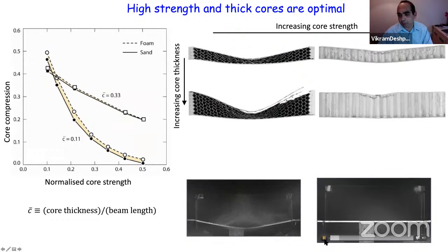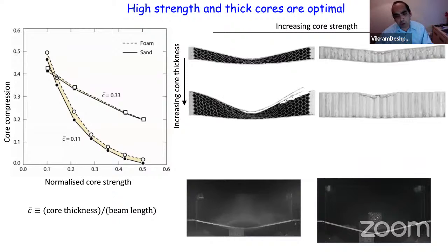And this is the foam impact equivalent. What you can see now is that a piece of metal foam is doing something extraordinarily similar to the sand, in that it's just compressing itself against the structure that it hits. And what I'm showing here is that if you take a metal foam of the same momentum as the sand, both via simulations and experiments, you're getting behavior that's very simple.